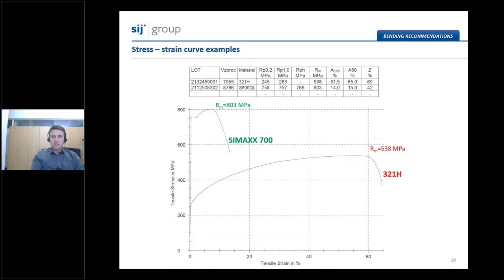On this slide, I would just like to show you an example of two different steels. So we have two stress strain curves. The green one is a stress strain curve of SIMAXX 700 grade, with the typical mechanical properties according to the standard requirements. And the ability for cold forming, so the bending, is correlated with the elongation, and for this steel, it is approximately 14%. The next curve, which has a completely different shape, is a stress-strain curve of austenitic steel.